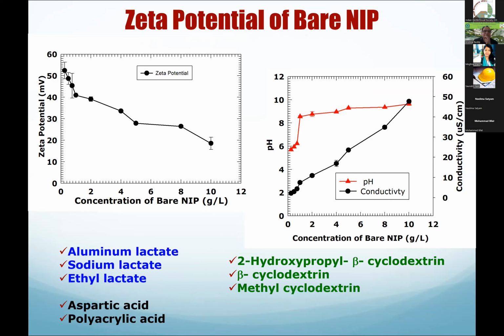So what we do is we try to look at different types of amendments. So the reason here, see, concentration of the bare nip. So we have 2 milligrams per liter, 4 milligrams. So different concentrations we took, and we measure the zeta potential using the zeta meter. And you can see there's a lot of positive charge on these nano iron particles. You see the nano iron particles, you have a lot of positive charge, and the positive charge reduces as the concentration increases, right? And then the pH would increase here with the concentration, and then conductivity also increases with the concentration.